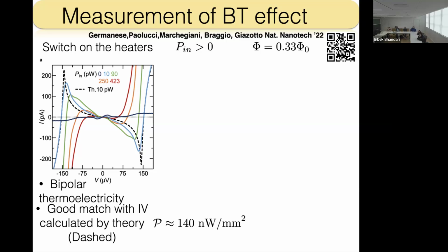And here you see again the important point. The solid curves are the measured IV curves for the system. And the different colors correspond to different power in the heating. So we made a heater on one side, we start to increase the power on the heater, and this creates a sort of gradient. And you see that this reduces with increasing power. That means that as you increase the gradient, at a certain point the thermoelectricity goes down.